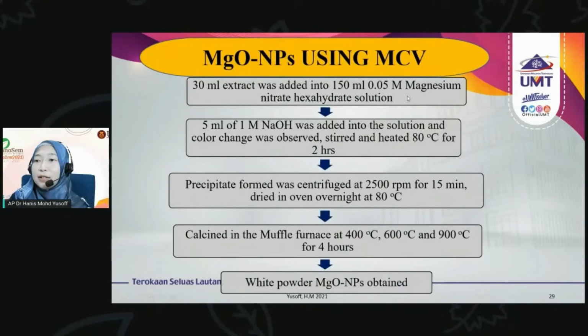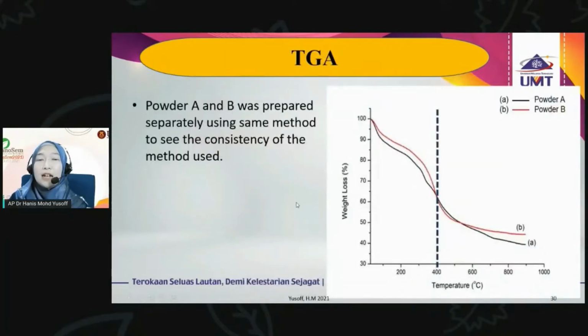The precursor or the starting material is magnesium nitrate hydrate, and then with sodium hydroxide, and these are the procedures. And of course, firstly, we monitored using TGA. So it is still not complete because we cannot do DSC yet, even until now. And it is important for us to monitor the consistency of the method when dealing with green synthesis. So that's why we synthesize these separately and try to see the TGA whether it is similar or not. So it seems like consistent.